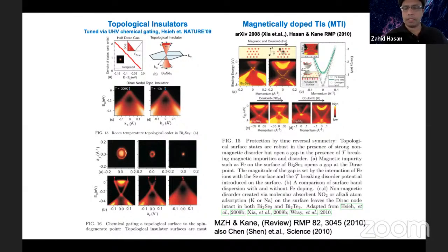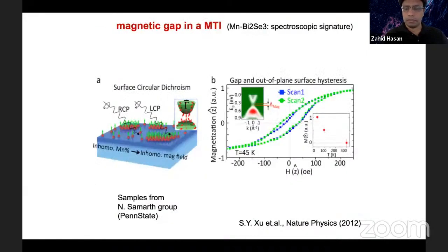Early on, before 2010, we could see some sort of gapping, but real materials in experiments are far more complicated. And we found examples where there is no intrinsic time reversal breaking, but the surface Dirac fermion can be gapped by chemistry. So the experimental connection to how to probe topological protection by time reversal symmetry is more complicated than the theory suggests. So we had to introduce a number of experimental algorithms to distinguish a gap, whether a massive Dirac fermion is topological or not.